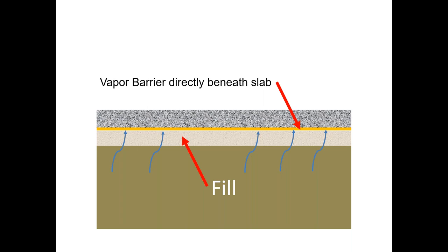Now I put down the ceramic tile, and I still do have efflorescence at a lot of my mortar joints, which I have to go back through periodically and clean, because as vapor comes up through the slab, it drags with it minerals and salts that dry on those grout joints in the form of efflorescence. But typically, if you've got that type of moisture drive issue, the only way to really solve it, if you want to put moisture sensitive flooring down, is to put down a moisture mitigating coating like the one that I showed you at the end of the presentation.